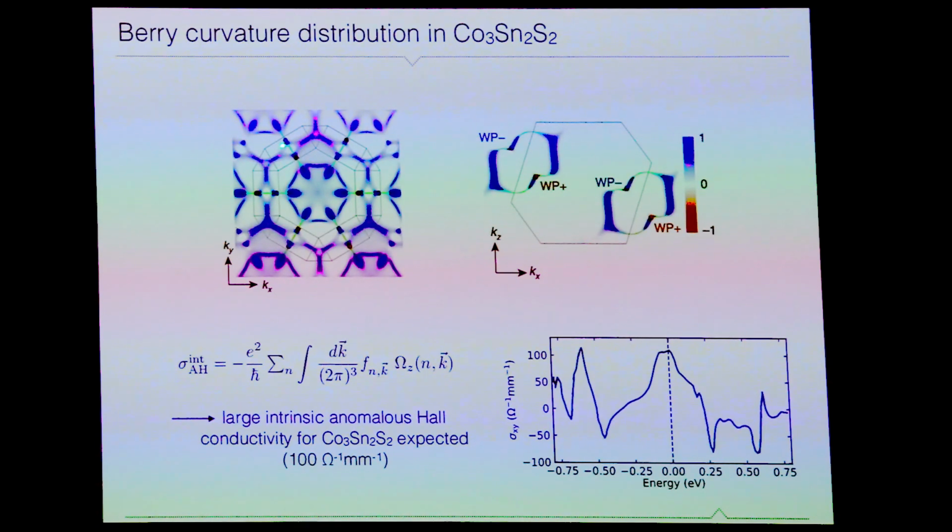And you can see this is the Z component of the Berry curvature, where the blue indicates the magnitude of the Z component mapped onto the YX plane. You see that is the position of the nodal rings, or the nodal lines, which would be there if they are not gapped. And the dots are the Weyl points.